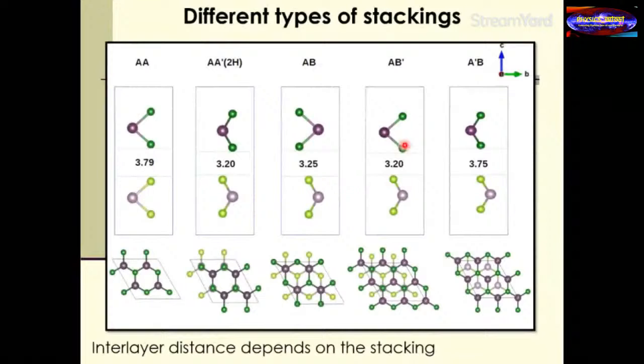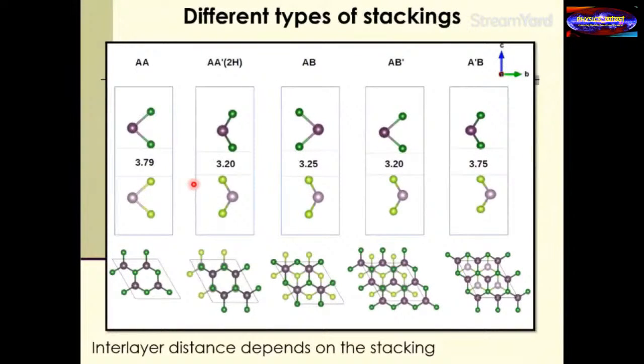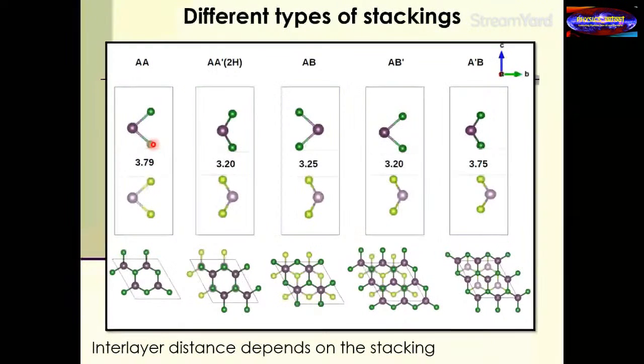Okay, you see over here, you have large patches, particular regions. What does it imply? If you look at this particular configuration with the anions sitting on top of each other, the electrons over here are repelling the electrons on this particular atom, and as a result, the two layers would like to stay further apart. The separation, measured by this distance of the outermost atoms in each layer, is about 3.8 angstroms. When I have these staggered kinds of configurations, the repulsion is much reduced, and as a result, the separation is about 3.2 angstroms.